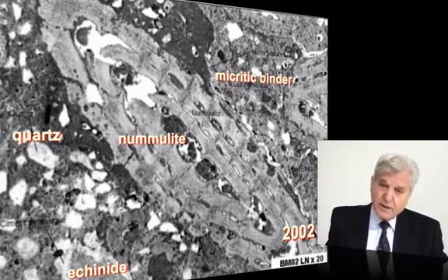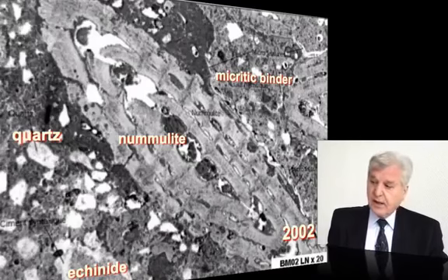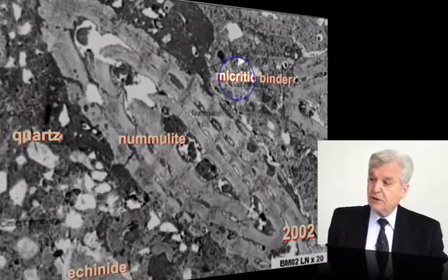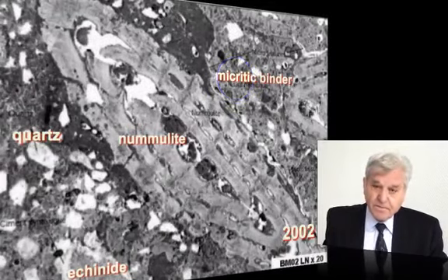This piece of artifact was made in our lab and had up to 10% by weight of modern geopolymer. They could not detect it under the optical microscope. The binder that we used to reagglomerate the stone was claimed to be natural micritic binder. So if I don't tell that the piece of limestone has been made in our laboratory, geologists and mineralogists will state that it is a natural stone, and this is also the case for the samples that we got from the Egyptian monuments.